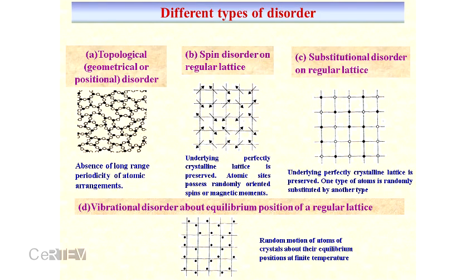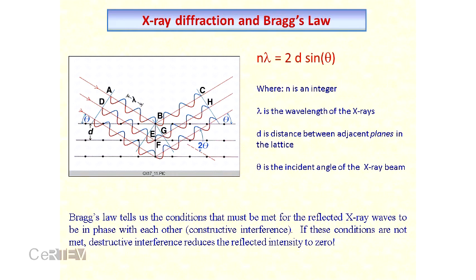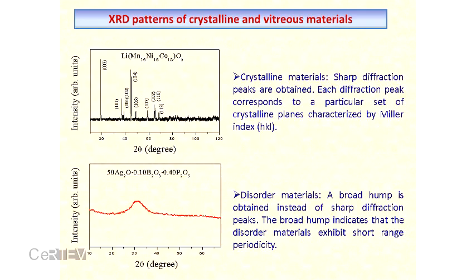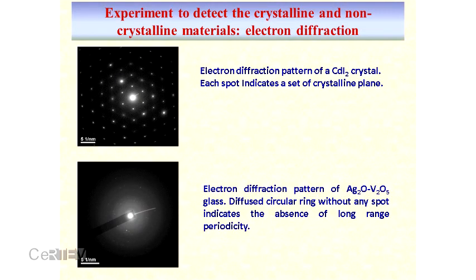Because this has already been discussed, first when we have a glass, we have to check whether it is a glass or crystal. So there are two ways. One is X-ray diffraction, where we get a very different pattern in XRD, as well as the modern technique of electron diffraction. Here for crystals we get distinct spots. Each spot indicates a set of crystalline planes, whereas in glassy materials we have a diffuse ring. But I am sorry that the figure is not clear. You can have diffuse circular rings without any spot, which indicates the absence of long-range order in the material.